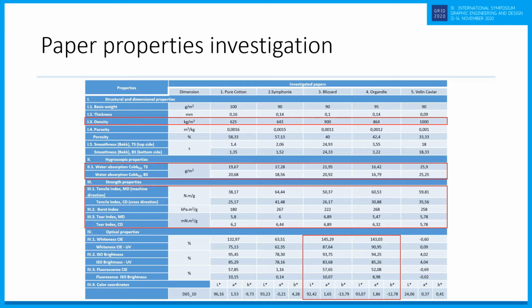The smoothness of the paper is the most important characteristic for engraving printing, which means that the most suitable could be Blizzard paper. From the Cobb analysis, it is seen that Blizzard paper has the optimal Cobb values for offset printing, around 22 grams per square meter, and we could expect excellent offset printability, followed by the pure cotton paper.